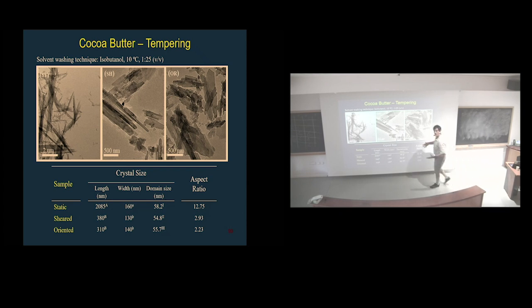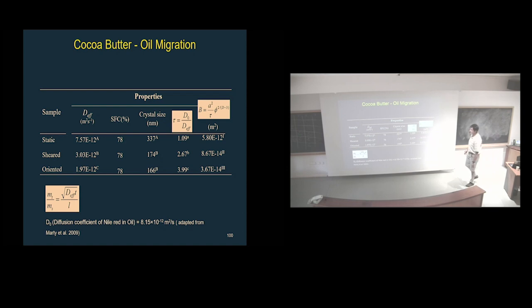Look at that chocolate. When you crystallize chocolate, you have these gigantic needles in the micron range. You start putting it in a shear field, or a laminar shear field, and you immediately go from microns to nanometers in the length. Let's just focus on the length. So you change the aspect ratio when you temper chocolate. And you can affect things like effective diffusion coefficients of oil, if you got static, sheared, oriented. Same amount of solids, very different crystal sizes.